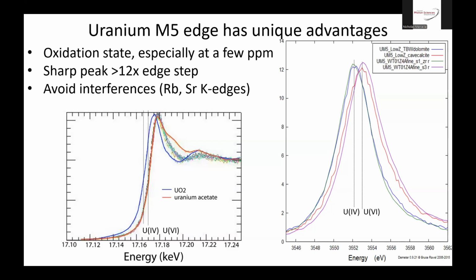If you know something about material properties. Just a little bit. At the L edge, you have to worry about rubidium and strontium, which are common elements in the same samples, and they do interfere. At the M edge, the only common interference that I've run into is silver, which is relatively rare, although Troy will attest to running into that problem at some point. The samples from a silver mine.